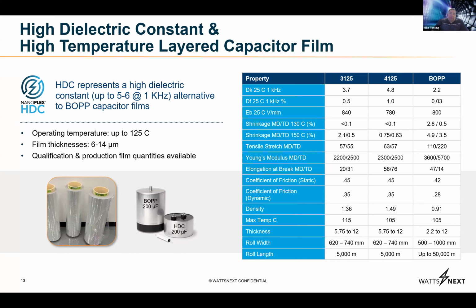And then when you start to look at the properties and compare them to the state-of-the-art BOPP, we have two grades of HDC. We look at 3125 and 4125. They come with higher dielectric constant, that's your DK. So 2.2 is the industry standard BOPP. Our HDC can be 3.7 to 4.8. It has similar electrical breakdown, so you can run it under similar voltages. But again, the max temperature of capacitors we've made out of these exceeds BOPP, and the films themselves go above 125 C without any issue at all. One of the trade-offs you do have, because in the real world you do have some trade-offs with materials, is that the electrical losses or efficiency of HDC is a little bit lower than BOPP. It's similar to a PET material, but still with a higher dielectric constant. So you balance that out.